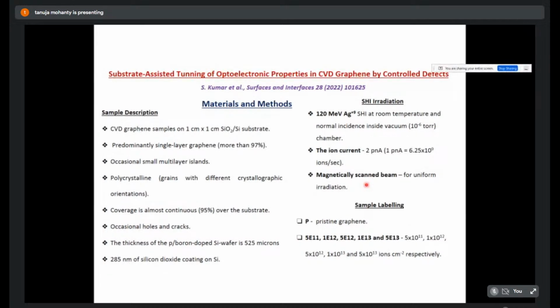Now we'll start with as much as I can cover. We'll start with what happens if we irradiate graphene, because as I said, it is a 2D material. Normally the graphene is CVD grown, which means chemical vapor deposited graphene samples. They are about 1 centimeter by 1 centimeter on a substrate, and the layer is a single layer or bilayer. And we use swift heavy ion irradiation with 120 MeV silver ions, as the facility gives it, at IUAC, Inter-University Accelerator Center, Delhi. And as I said, this is the minimum.